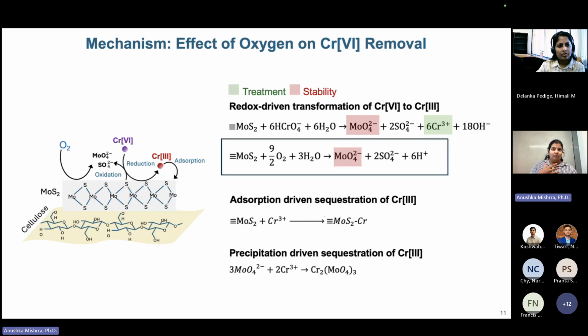Our hypothesis was that the oxygen in the water was reacting with MoS2 to create more molybdate species. There is also some preliminary work showing that MoS2 can be oxidized in water, so we wanted to study this and see if our hypothesis was correct.